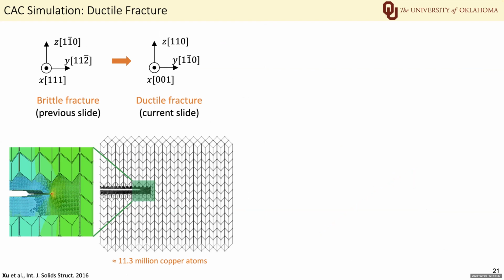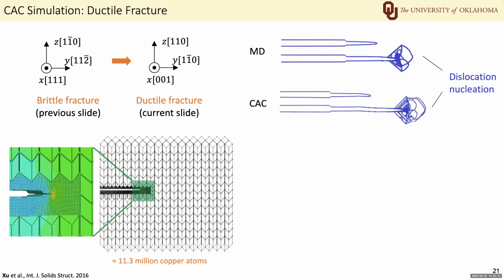So if I change the lattice and orientation of the system to one that favors the dislocation nucleation, the brittle fracture would become the ductile fracture. And again, the entire system is modeled by a coarse-grained domain except around the crack. And unlike the case of the brittle fracture on the previous slide, here, as the crack propagates, the dislocations are also nucleated from the crack tip. And this phenomenon is well captured in the CAC simulation with the help of the adaptive element refinement.